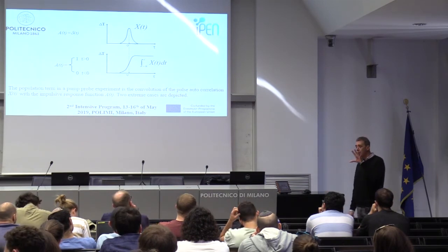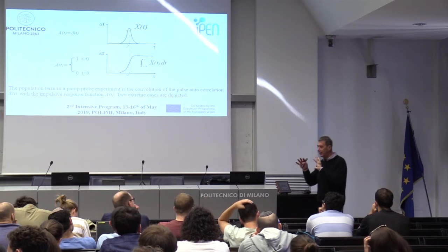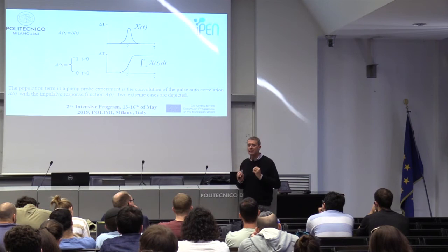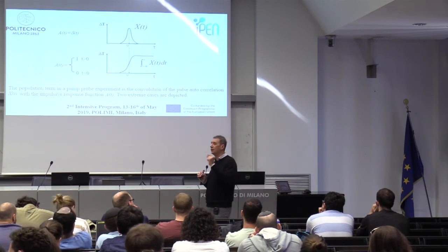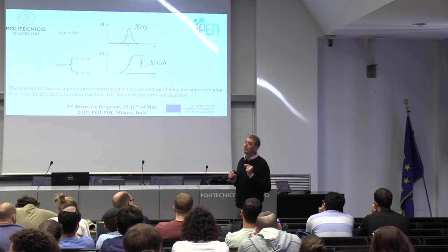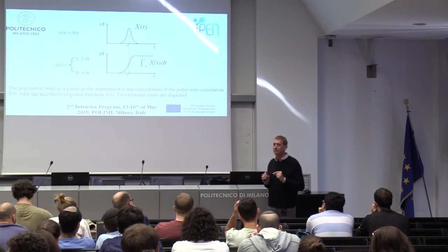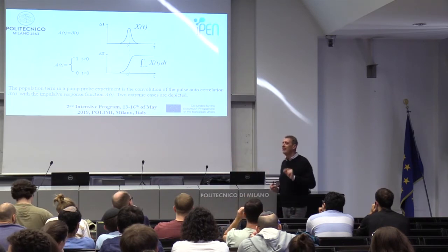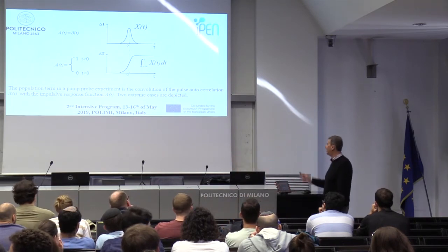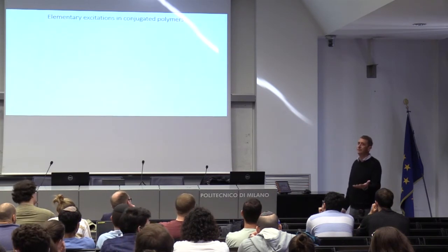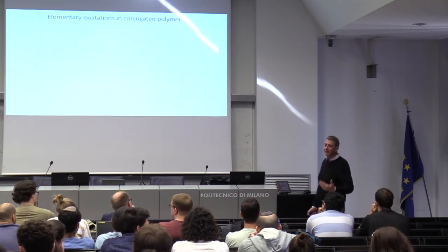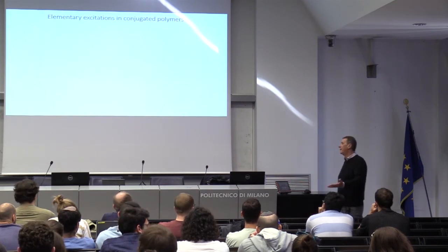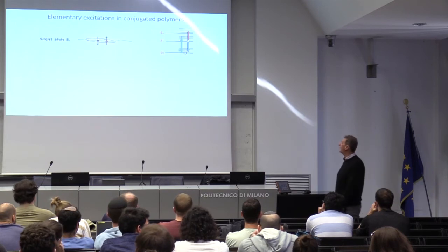Then there are people that still go inside the shape and, knowing the pulse correlation, extract information. But personally, I do not believe people that report time constants which are shorter than the pulse. In principle, if you have zero noise, you can do this, because you see the mathematics, you can. The correlation is changing a bit, but it is never zero noise. So I don't believe it; it's much better to make shorter pulses. If you want to measure something faster, you go with a laser which has short enough pulses. If your pulses are too long, you look for pulses that are short enough.